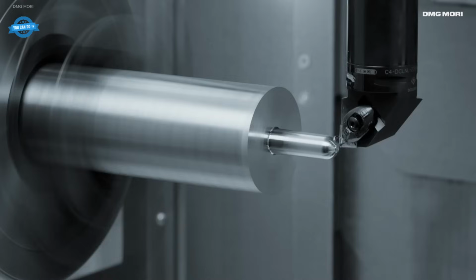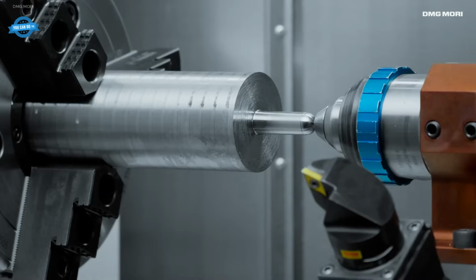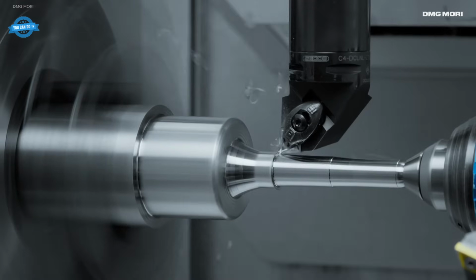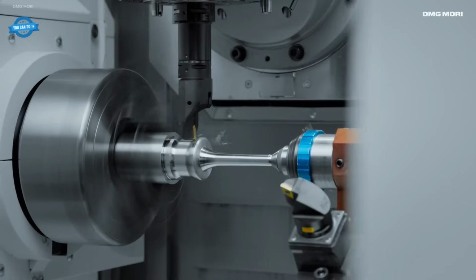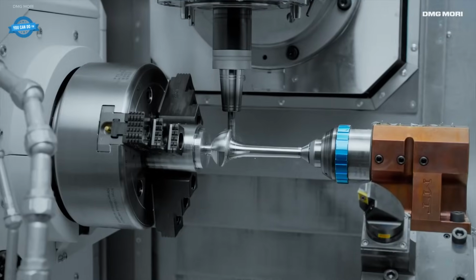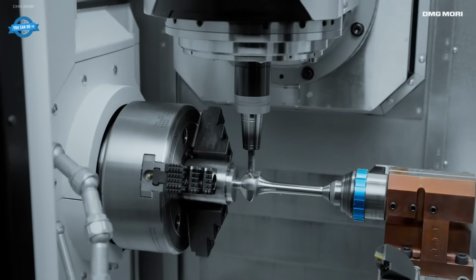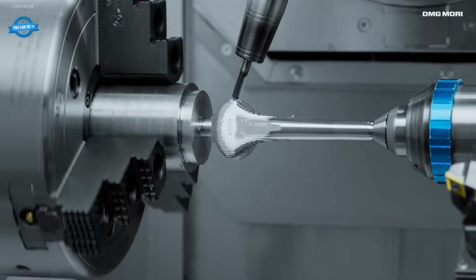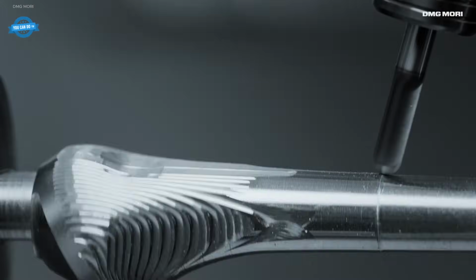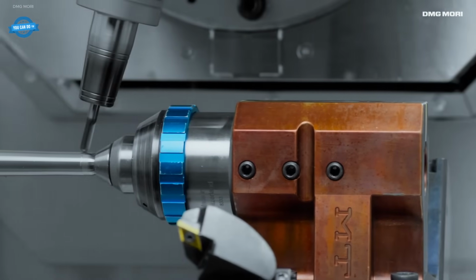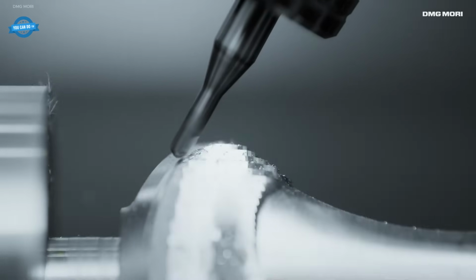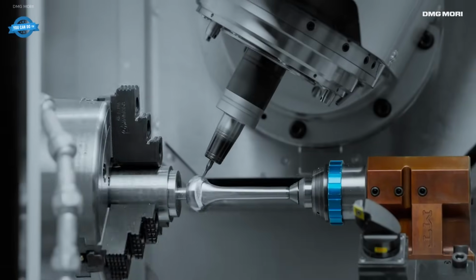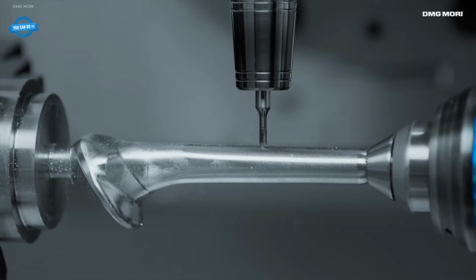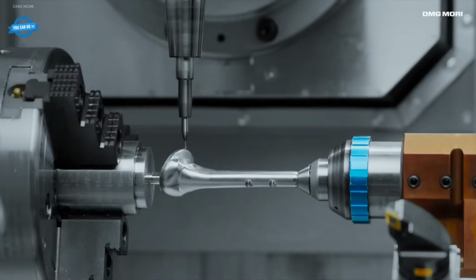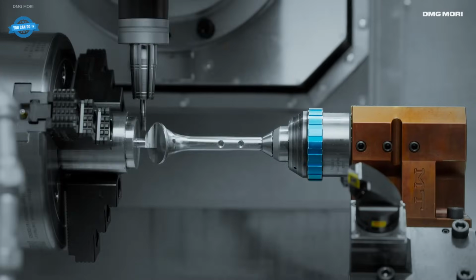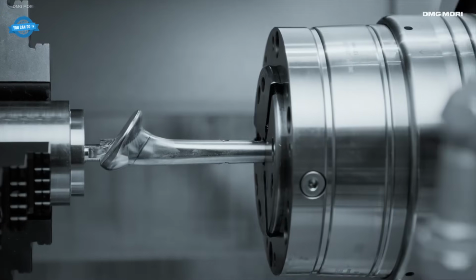The titanium shoulder implant is fully machined on the NTX 1000 using 6-sided turning and milling. The process begins with rough turning of the cylindrical blank, followed by multi-face milling using simultaneous 5-axis machining. Complex contours are precisely formed by the direct drive motor in the B-axis, while high-speed spindles ensure smooth surface finishes. Final finishing includes contour refinement and drilling. The in-machine robot unloads the completed implant automatically, ensuring consistent precision and efficiency.